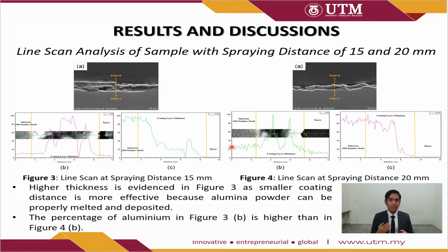Higher thickness is evident in figure 3 as smaller coating distance is more effective because alumina powder can be properly melted and deposited. Next, the percentage of aluminium in figure 3B is higher than in figure 4B. This is due to the fact that there is a formation of coating layer which is denser than the coating produced at longer spraying distance. Next, the temperature of the deposited particle is higher in shorter spraying distance.